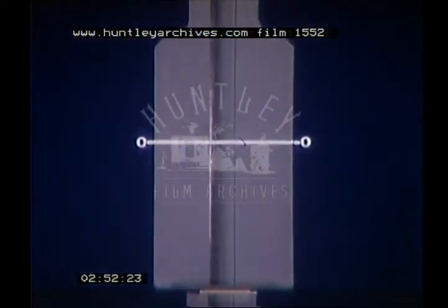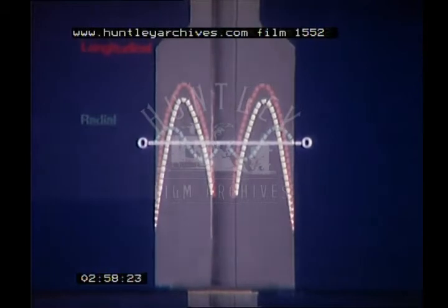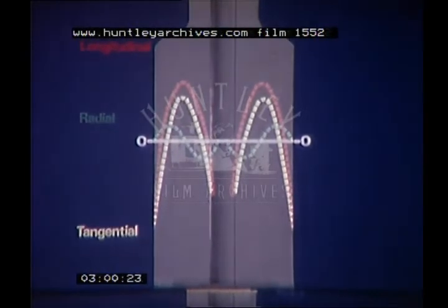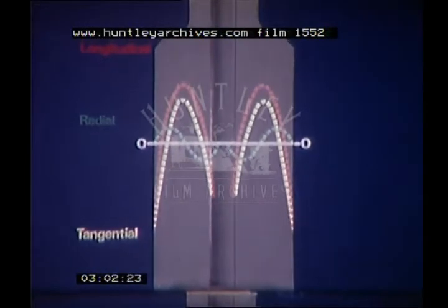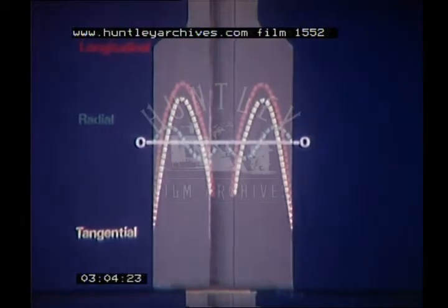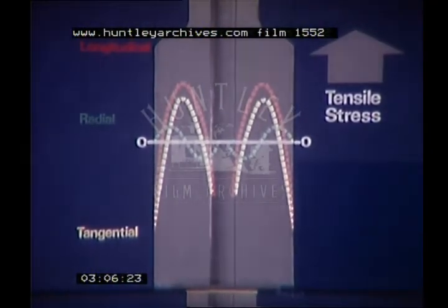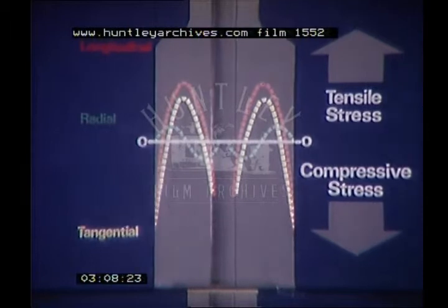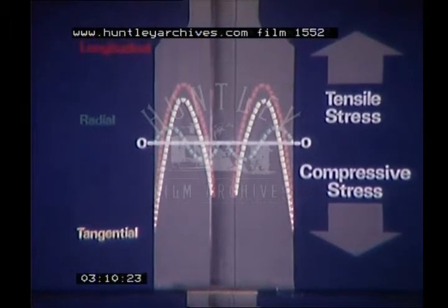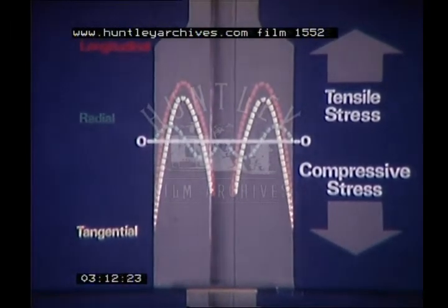If a hole is bored down the center of the roll and water quenching introduced there also, the stress system is quite different. The dangerous tensile stresses have now substantially decreased in value, but more important, they have moved to the mid-radius position with both the surface layers and the bore in compression, eliminating the possibility of fatigue failure from the bore surface in use. This is the basis of the classical hardening technique.